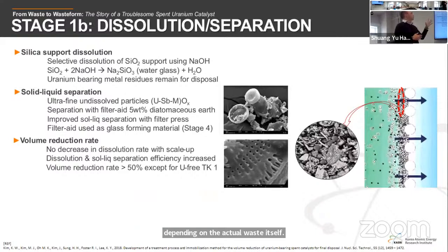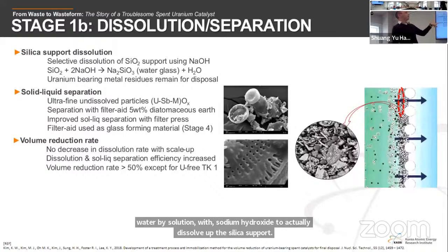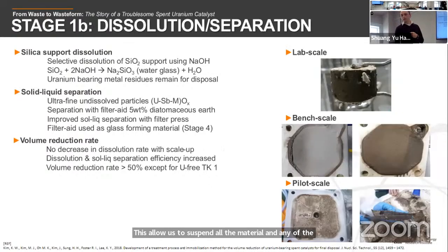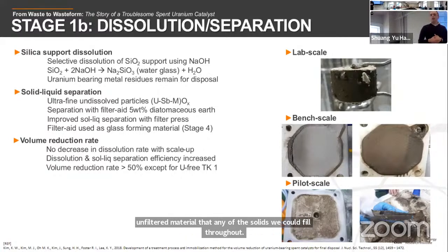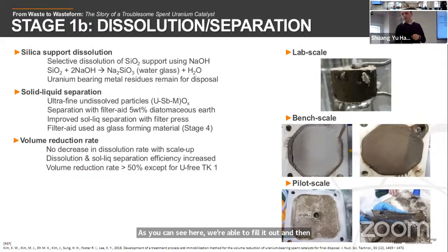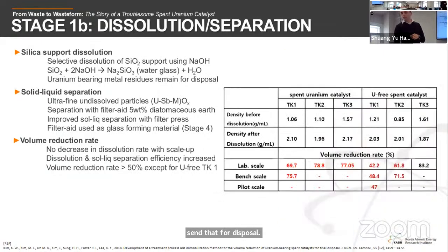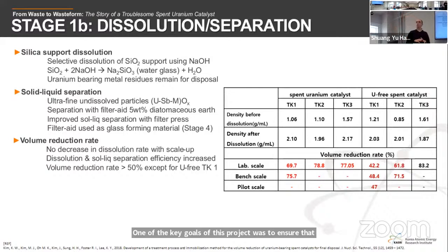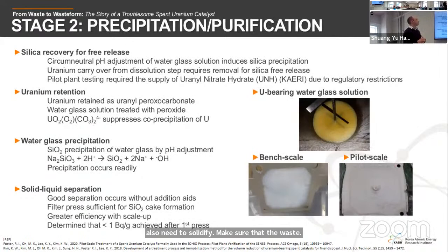This could then be dissolved using water glass solution with sodium hydroxide to dissolve the silica support. This allowed us to suspend all the material, and any of the unfiltered material, any of the solids, we could filter out. As you can see here, we're able to filter it out, and then send that for disposal as a glass ceramic in the final stage. We found that as we scaled up to the different scales, we got good volume reduction. One of the key goals of this project was to ensure a good volume reduction across the whole process. We obviously don't want to increase volume, but we did also need to solidify and make sure the waste was well contained.